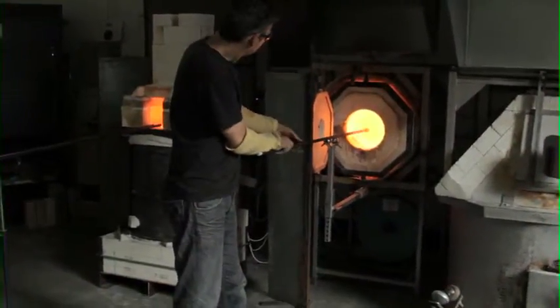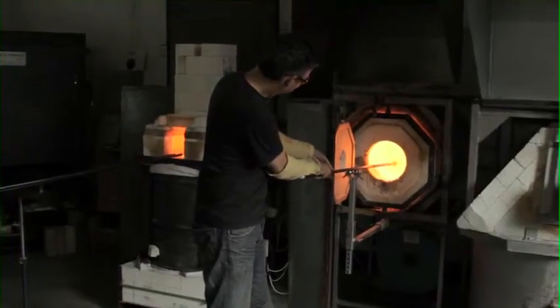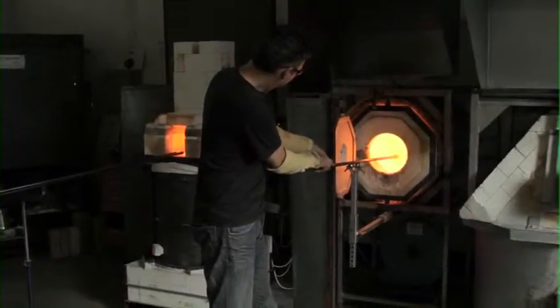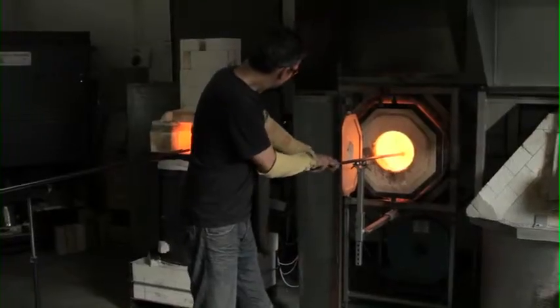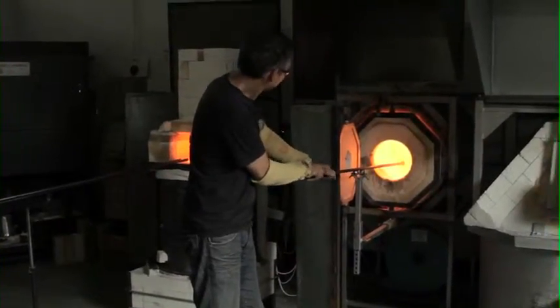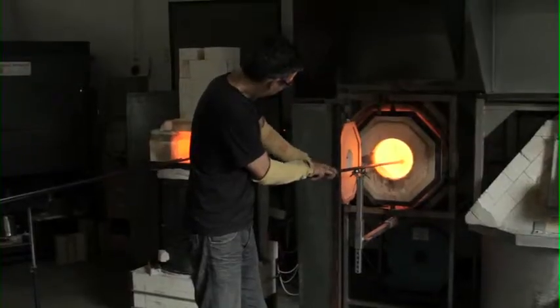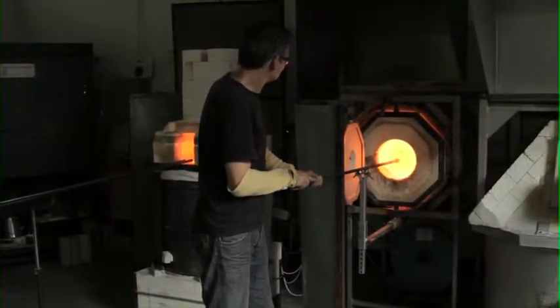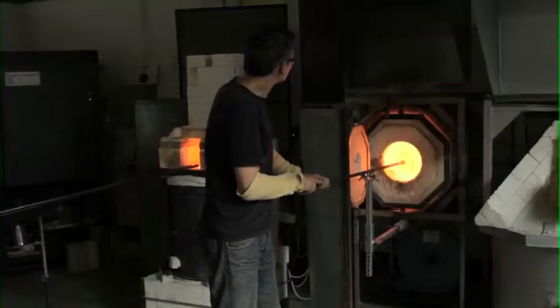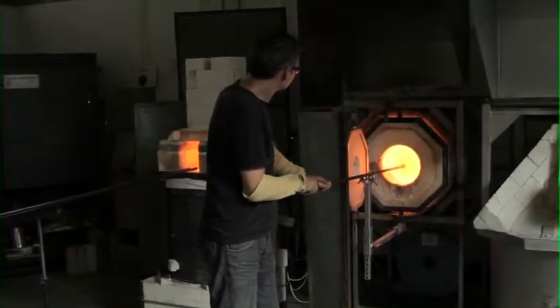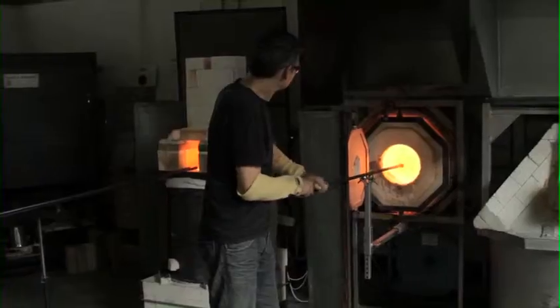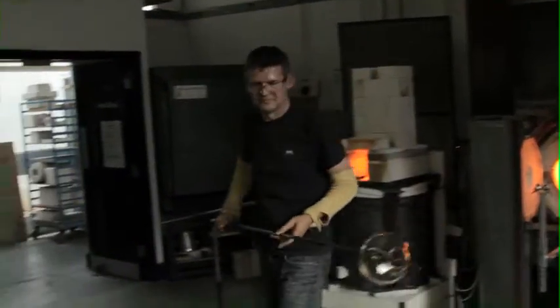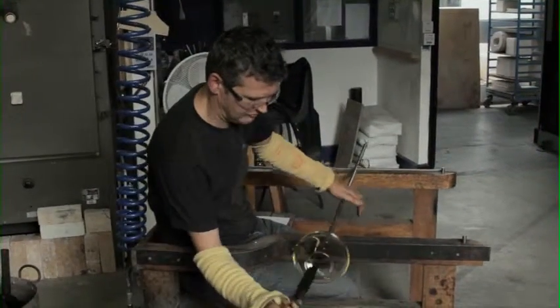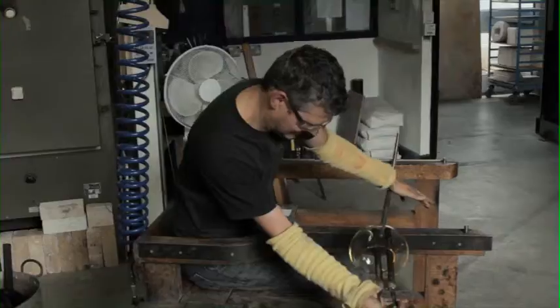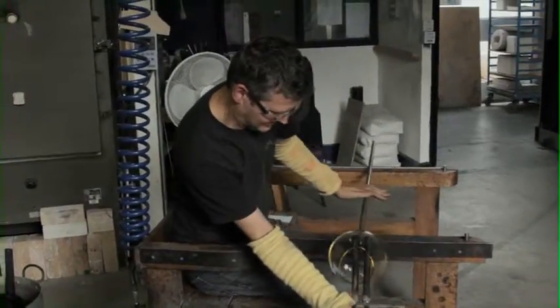I got better quality glass when I put most of the batch into the furnace in one hit, and then topped up the level a few hours later. Many glass makers who follow the recommendations have reported flaws in the melt, which are in fact deposits from the pelletized bonding material trapped in layers throughout the melt. I know through experience that working with different designs of pot furnaces, it is in many cases better to reduce the melting temperature and increase the soak time. This reduces the chance of anything going wrong with the melt, such as the introduction of cord, and ensures that bubbles and seed are eliminated, and greatly extends the working life of the crucible.